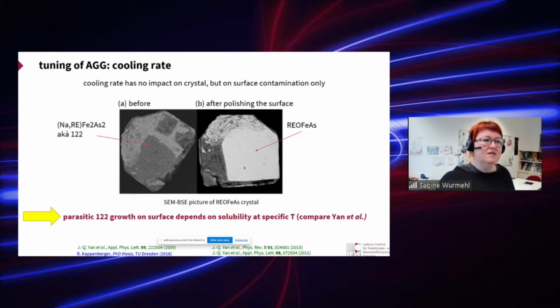This tells us also that your crystal is already fully grown at the highest temperature due to the diffusion control process, and only upon cooling down do you crystallize from the sodium arsenide your parasitic 122 phase.